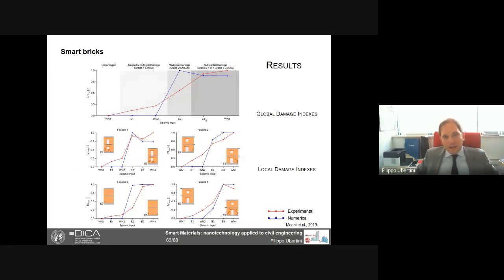And here you see a comparison with the real damage, in gray: undamaged is white, negligible to slight damage is light gray, moderate damage is moderate gray, and substantial damage, which however is far from the ultimate limit state condition, is darker gray. I have to say we never reached collapse here, we did not even get close. You see with the red line, as a function of the different seismic inputs, what we get from the experiments in terms of damage index, and with blue what we get from the numerical simulation.